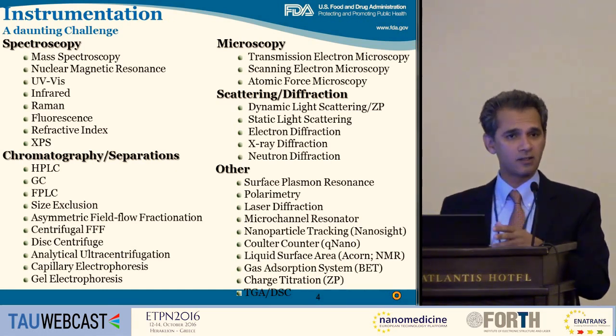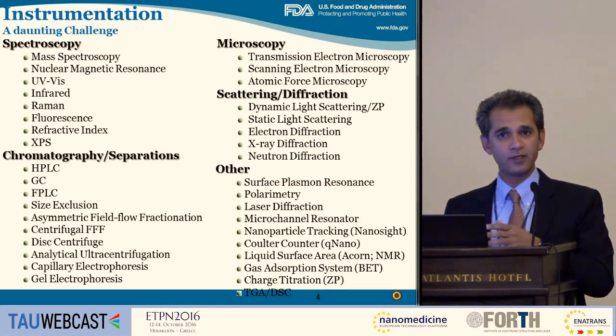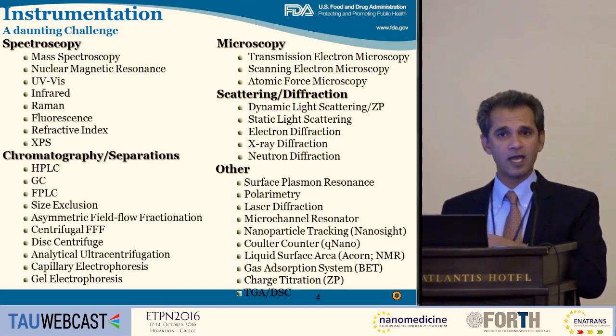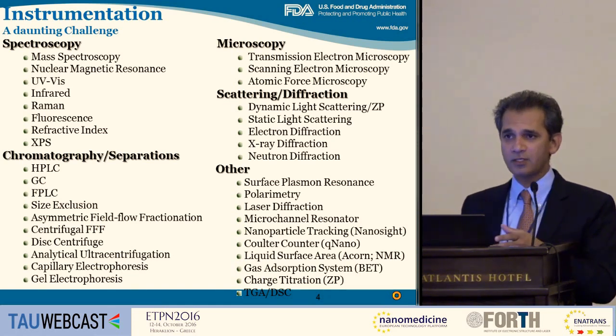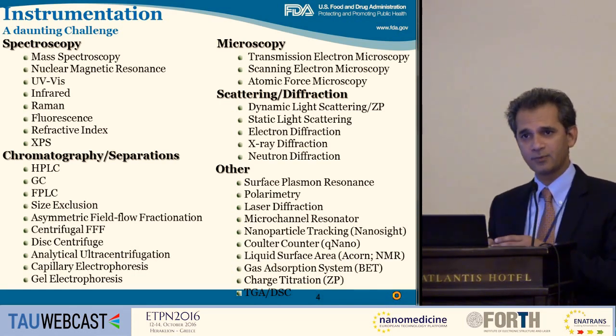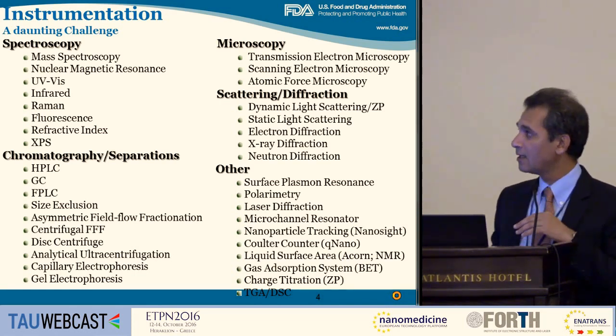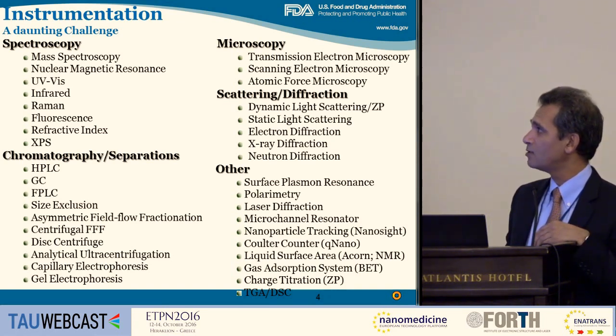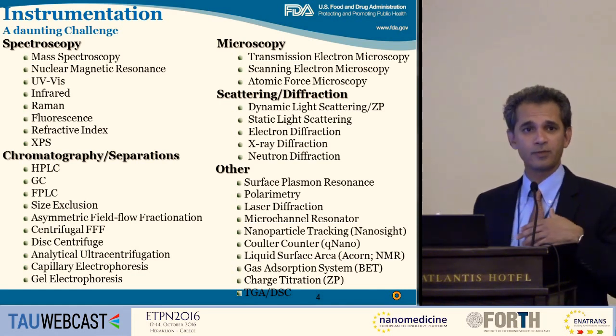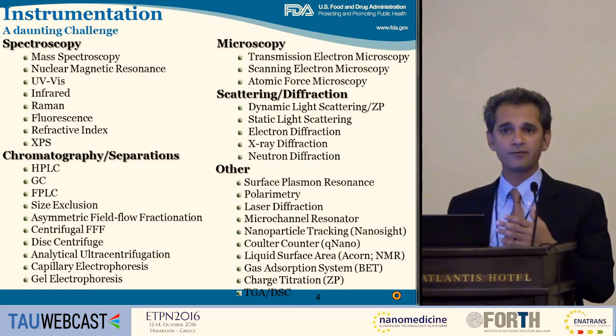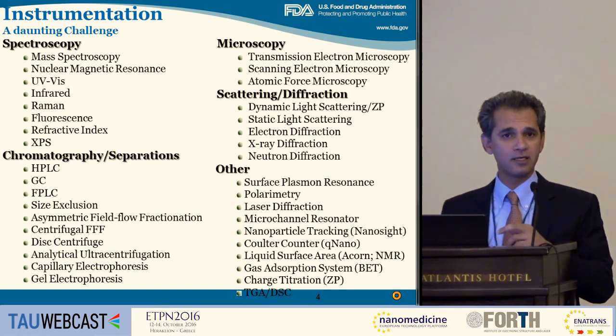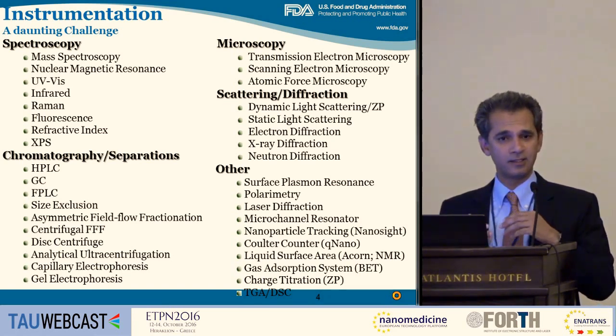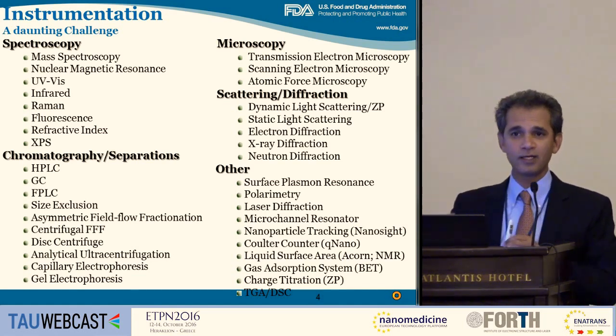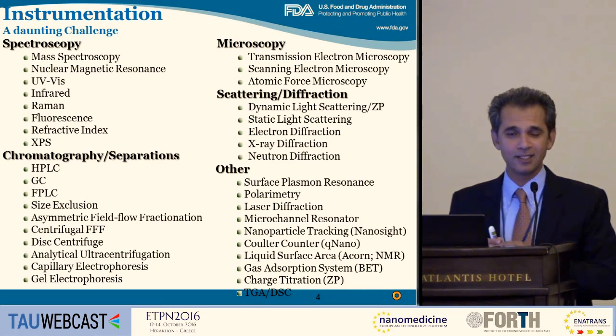SEC or size exclusion or gel permeation chromatography can be used for certain kind of nanomaterial, whether they're polymers, dendrimers. You can define the polydispersity, purity using some of these techniques. The batch mode measurements using dynamic light scattering, it is very simple. Most people use, and we actually looked at a lot of submissions that are considered nano, and they use dynamic light scattering. It is a very simple technique. You put the vial in, cuvette, and then press a button, it will give you a size.